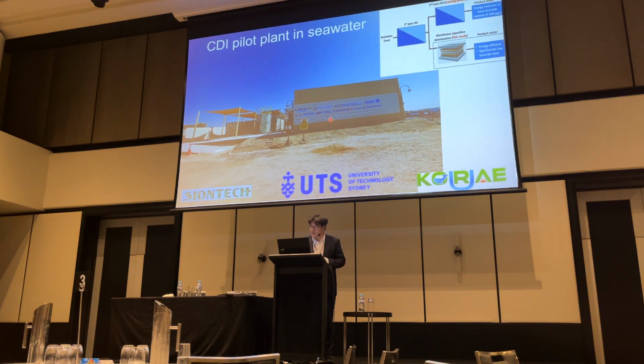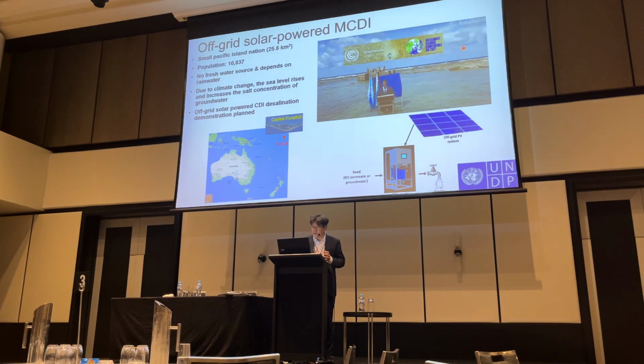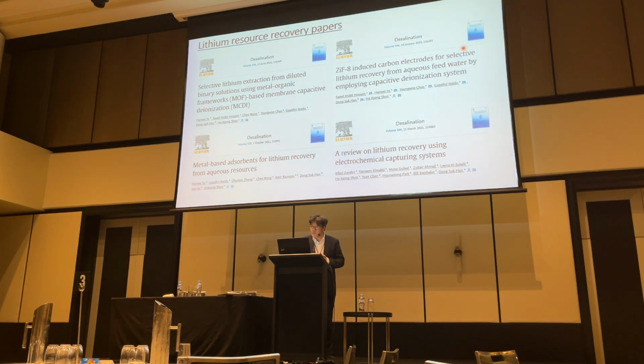We have experience for the last 5 years. We have applied CDI for low energy desalination to replace second pass RO, and we have saved around 0.3 kilowatt hours per cubic meter in a desalination plant. We have also collaborated with the UNDP for Tuvalu, because their country is sinking due to climate change and ocean level rise. We would like to provide them desalination using this CDI. So we are working with the UNDP, and this is our first lithium resource recovery. We have published, so if you need more details, you can find them in these papers.